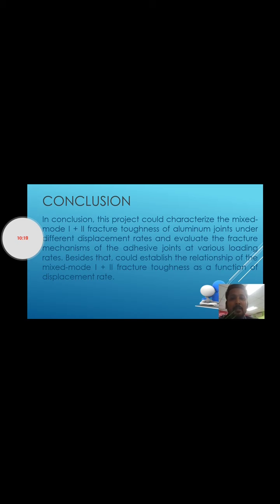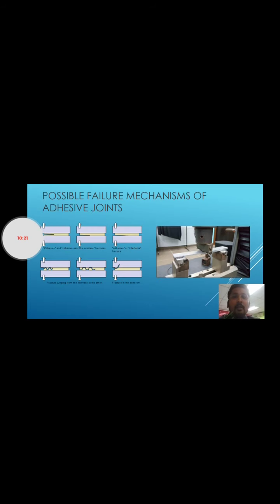And then next we have to characterize the failure. For 5 mm, we found adhesive or interfacial fracture. For 50 mm, we found fracture jumping from one interface to the other. For 500 mm, the cohesive near the interface fracture. How does it look? I give you another slide, my backup slide. Sorry.